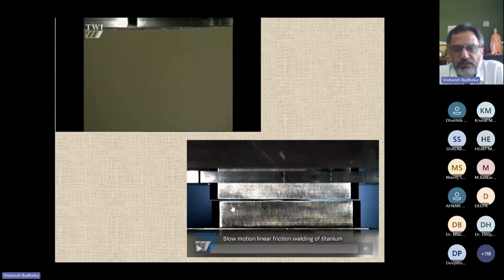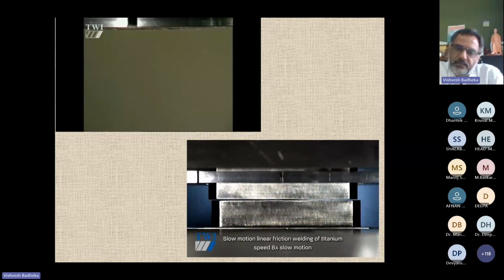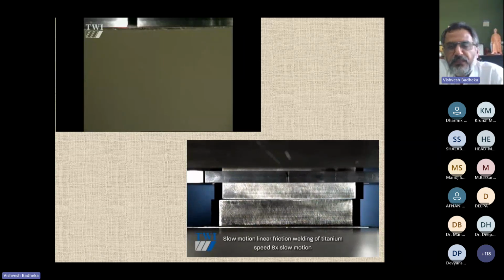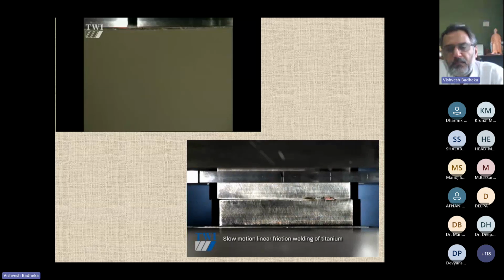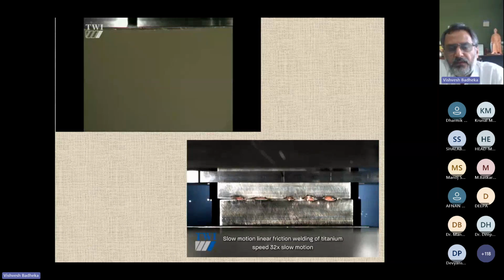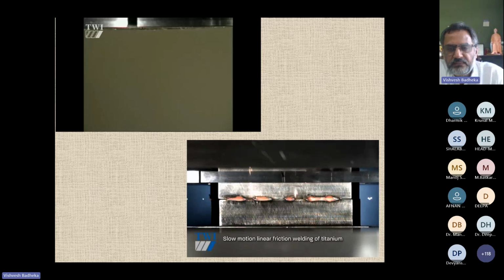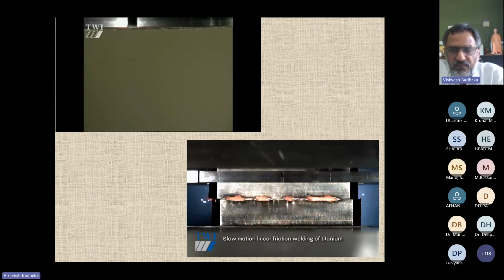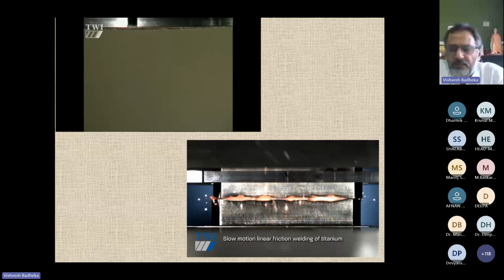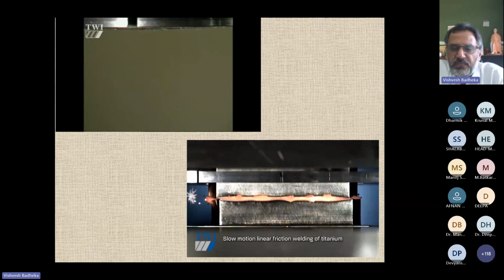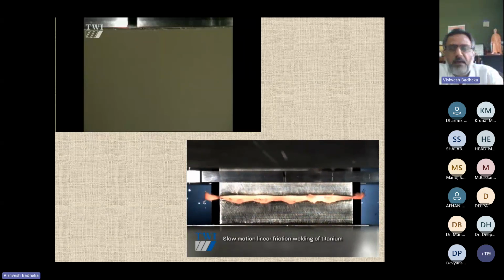So here, there is another possibility that you have. You see that there is a linear motion going on between the two interfaces. This linear motion may help you to develop red spots at certain intervals, and you can reduce the frequency further. These interfaces are rubbing against each other with a certain downward force. With the passage of time, these red spots are getting bigger and bigger, and the complete interface becomes red hot. This is how slow-motion linear friction welding is happening.